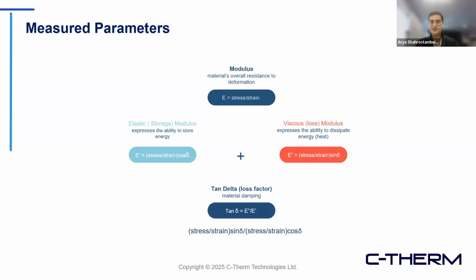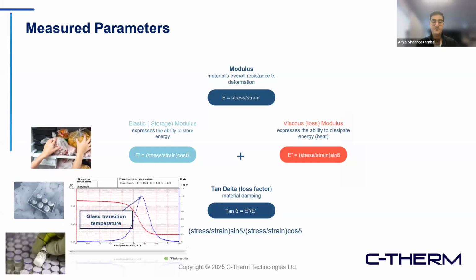And as you can see, these two different components can be very useful to express different behavior of a viscoelastic material. And we also have a very important parameter, which is called tan delta. This parameter is given by the ratio of loss modulus, or viscous modulus, over storage modulus, and it's called tan delta. And this parameter is very important for evaluating materials for different applications. For example, the most famous one is glass transition temperature. So basically running a temperature sweep test on a specimen, as you can see, gives you a peak in tan delta, and that peak is used to determine the glass transition temperature.